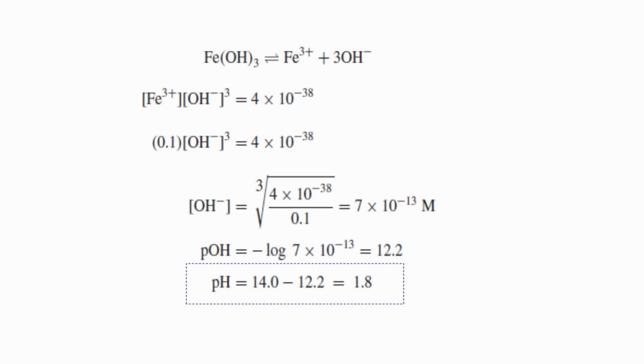When you dissolve iron chloride in water, it will surely hydrolyze to form iron 3 hydroxide, a rust-colored precipitate. To stabilize the iron 3 solution, you must acidify the solution, for example with hydrochloric acid. Note that precipitation generally will not occur exactly at the calculated pH, as supersaturation is needed.